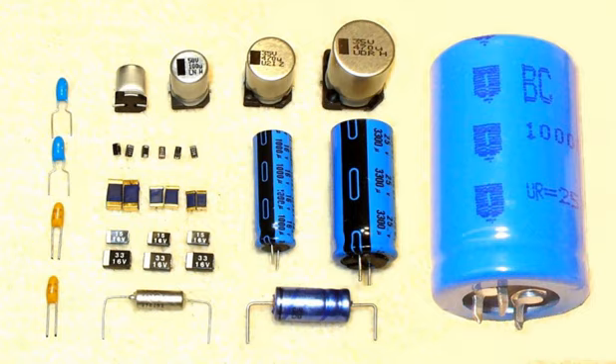Water-based electrolytes. With the goal of reducing ESR for inexpensive non-solid E-caps, from the mid-1980s in Japan new water-based electrolytes for aluminum electrolytic capacitors were developed. Water is inexpensive, an effective solvent for electrolytes, and significantly improves the conductivity of the electrolyte. The Japanese manufacturer Rubycon was a leader in the development of new water-based electrolyte systems with enhanced conductivity in the late 1990s. The new series of non-solid E-caps with water-based electrolyte was described in the data sheets as having low ESR, low impedance, ultra-low impedance, or high ripple current.